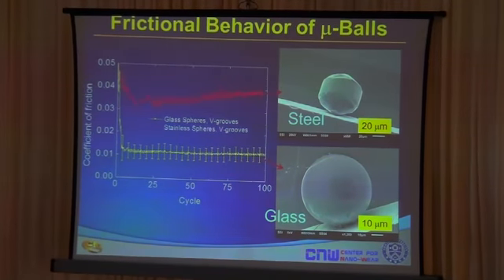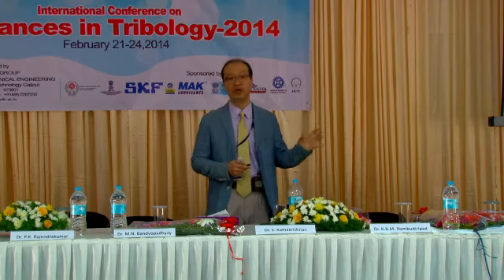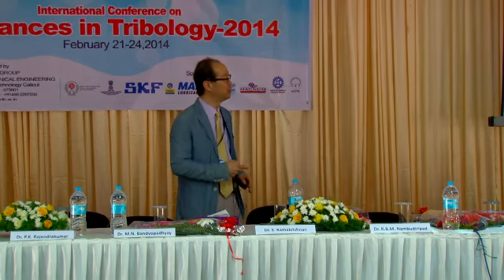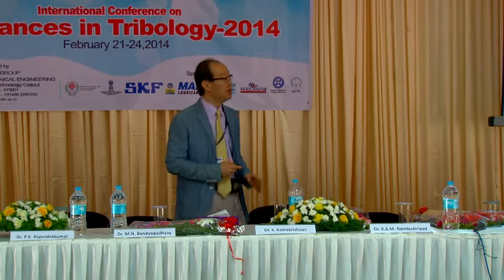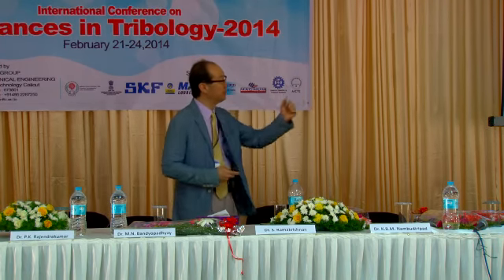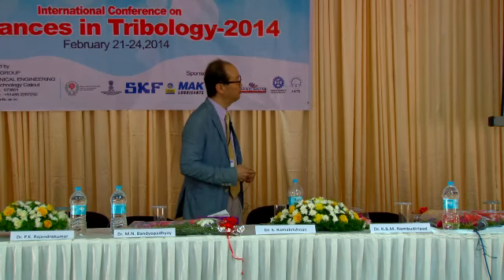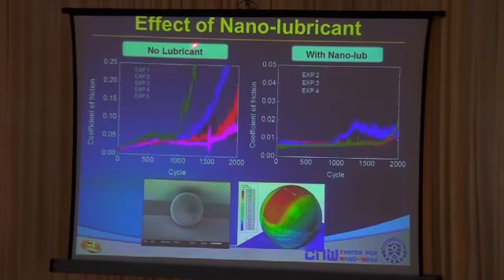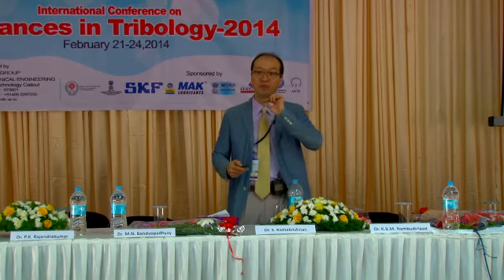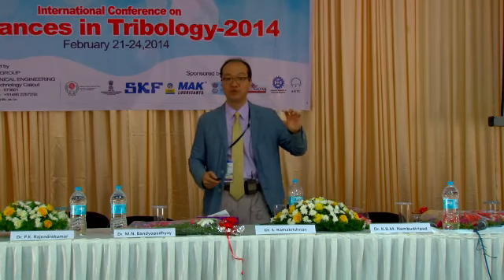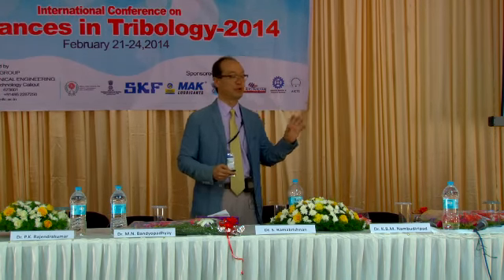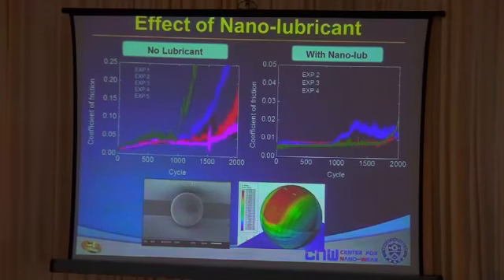In the case of the glass ball, the hardness is higher than the steel ball that we used, and in this case, we're able to maintain low friction coefficient to about 100 cycles. Of course, we're interested in much higher number of cycles, and this is a test that we did for about 2,000 cycles without lubricant and with lubricant. The lubricant that I call here is a nano-lubricant because it's not a liquid type of lubricant. It's the kind of lubricant that we use for hard disk drive. It's a one monolayer of organic film. So it's like a semi-solid type of lubricant. Its purpose is to reduce the stiction between the 2 surfaces.